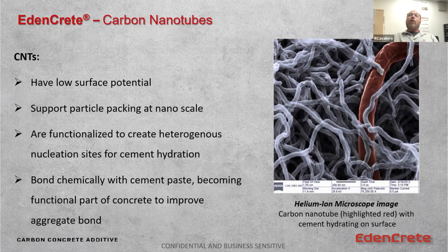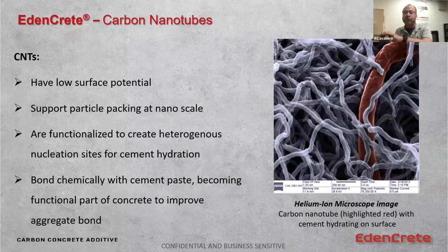Now, when we look at the carbon nanotubes and their function within the cement paste matrix, they're so small that their surface potential is almost negligible. And essentially that just means that, when we're making our product, we functionalize the carbon nanotubes. And when they have such a low surface potential and they've been functionalized, they become good candidates for heterogeneous nucleation sites. And that just means that the cement can actually attach and hydrate around or encapsulate.